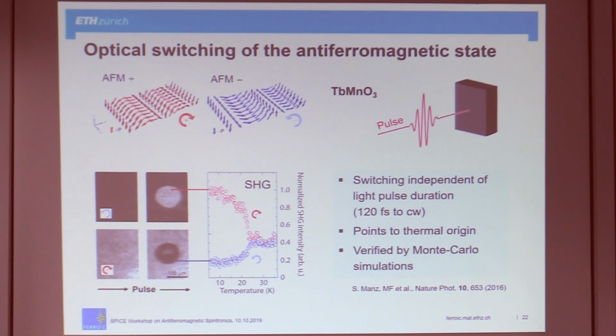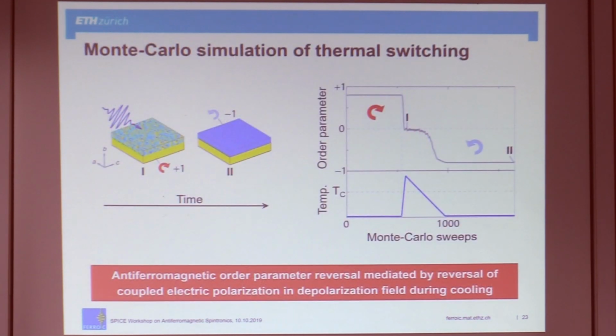So what we think we have is we heat up our sample locally, bring it from this antiferromagnetic and slightly polarized state into the paramagnetic, non-polarized state. Then we take our laser beam away, the sample cools down, and the depolarization field forces the polarization, and therefore the antiferromagnetic order, to reverse. That it can work like this, we also showed in Monte Carlo simulations. Here we have a sample in the yellow state, so it's one of these circular spin spiral states. We heat it up by a laser pulse. You have a disordered state. Then it cools down, and at least in the Monte Carlo simulation, it reverses its polarization and therefore antiferromagnetization. So in the computer, it works very nicely.